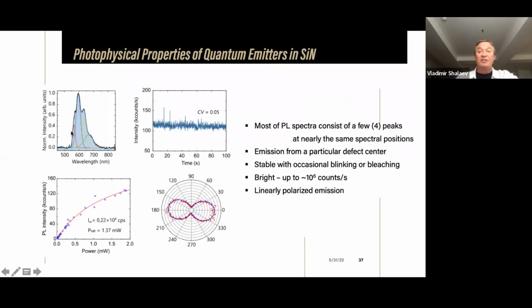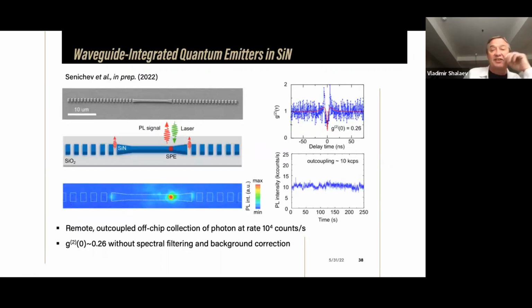So the spectrum, all this done at room temperature, it's important. Spectra look like an overlap between 4 different lines, and from point to point they reproduce, meaning this is one particular type of defect. They're stable, there is not much blinking as you could see, and the number of counts is approaching way above 10 to the 5, approaching 1 million counts per second. So we already successfully integrated the single photon emitters with a waveguide. Basically you excite this single photon emitter and it couples to the waveguide mode, and then you decouple with a grating and detect these single photons.